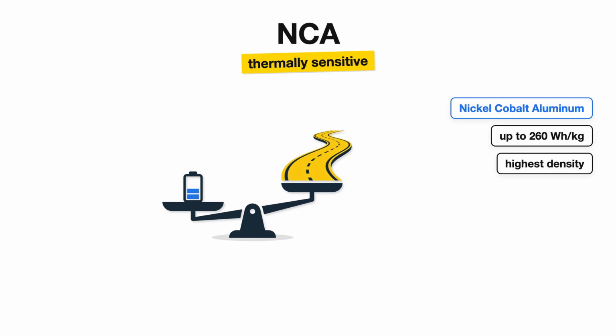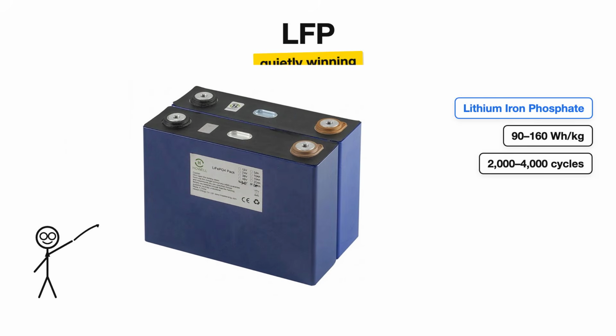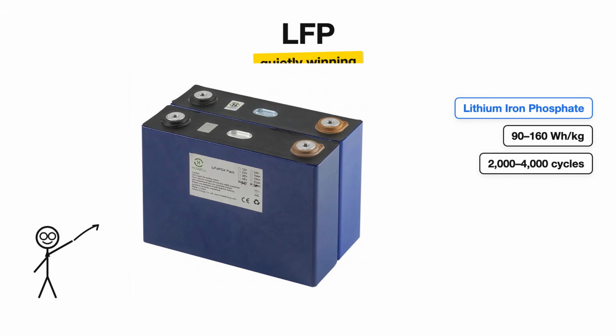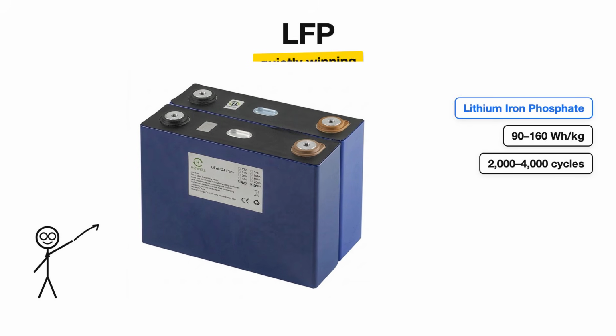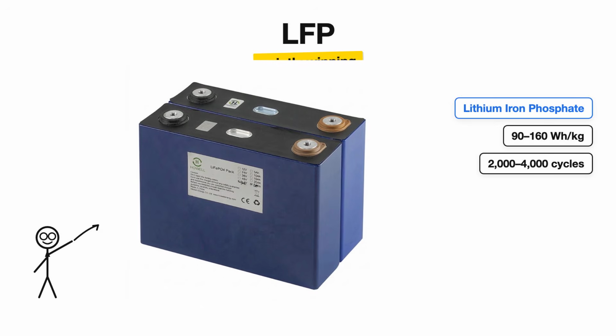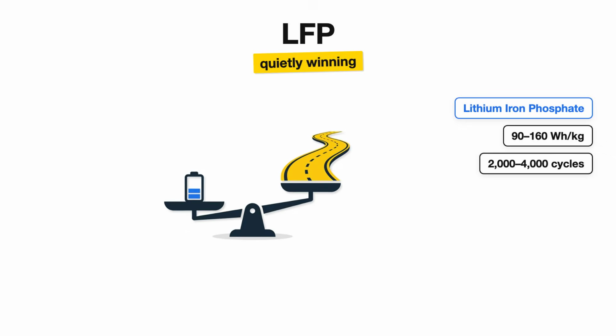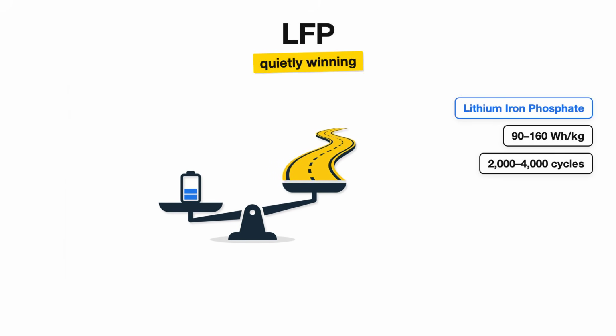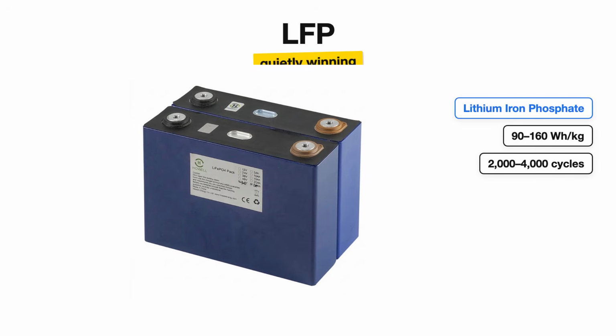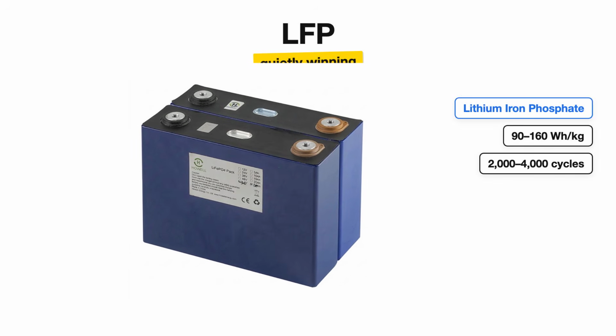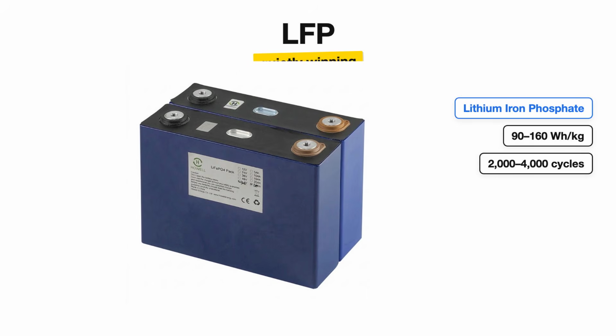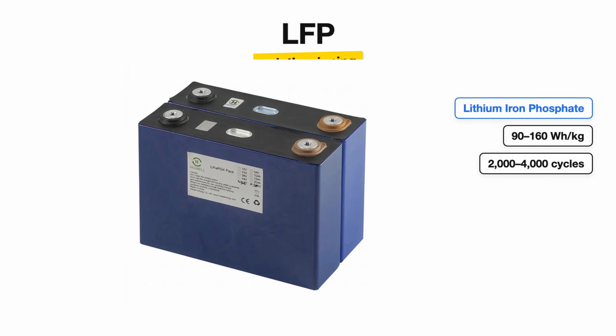Now here is the chemistry that is quietly winning, even though it should not be the obvious choice on paper. LFP, lithium iron phosphate. On the surface, LFP looks worse. Its energy density is only 90 to 160 watt-hours per kilogram, noticeably lower than NMC. For the same range, you need a heavier battery. Not great for a vehicle already carrying extra weight compared to a gas car, but here is what changes the story. LFP lasts far longer.